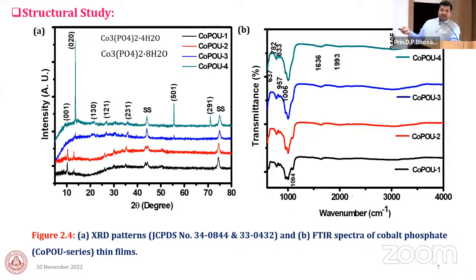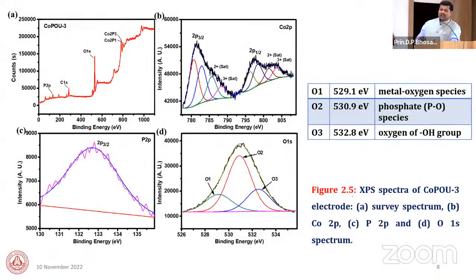When I studied the XPS of this material, it confirms the cobalt, phosphorus, and oxygen elements are present, and we acquired the cobalt spectrum, and it gives various oxidation states like 2 plus and 3 plus. The oxygen contains three deconvoluted peaks: the first one is metal oxygen, the second one is phosphorus oxygen, and the third one is the hydrous content of water molecules. So these three types of structural studies confirm the prepared material is cobalt phosphate with hydrous content.